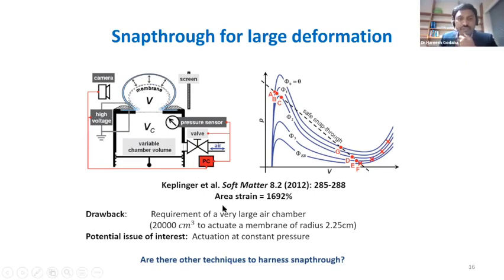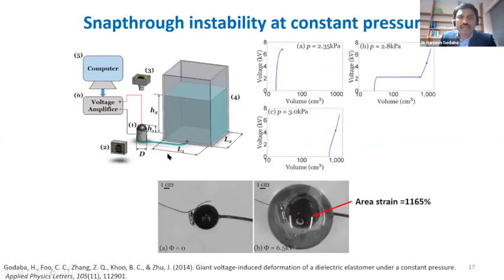So using this technique, quite a large area strain was achieved, but the drawback is that it needs a very, very large air chamber. For example, for a small balloon of radius 2.25 centimeter, we need a chamber of volume 20,000 centimeter cube. It is a very huge volume in comparison. So in my work, what we did was